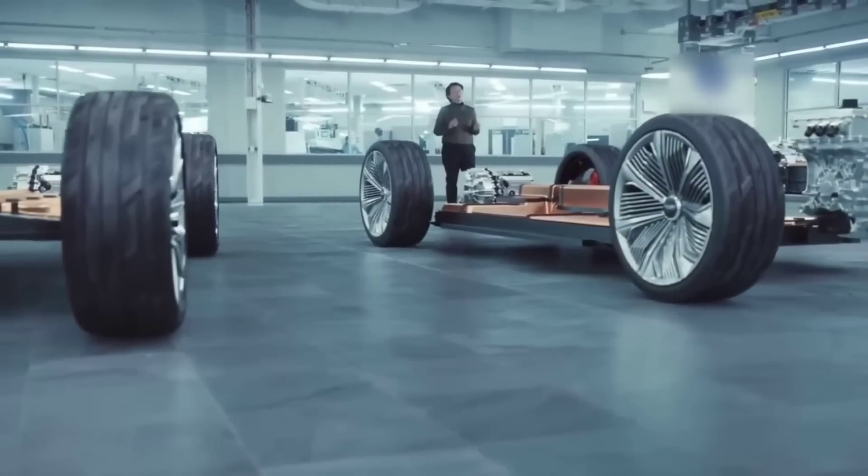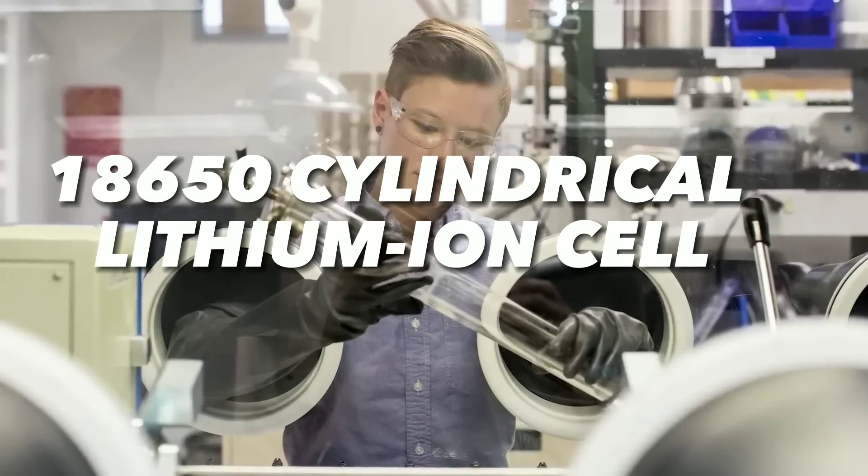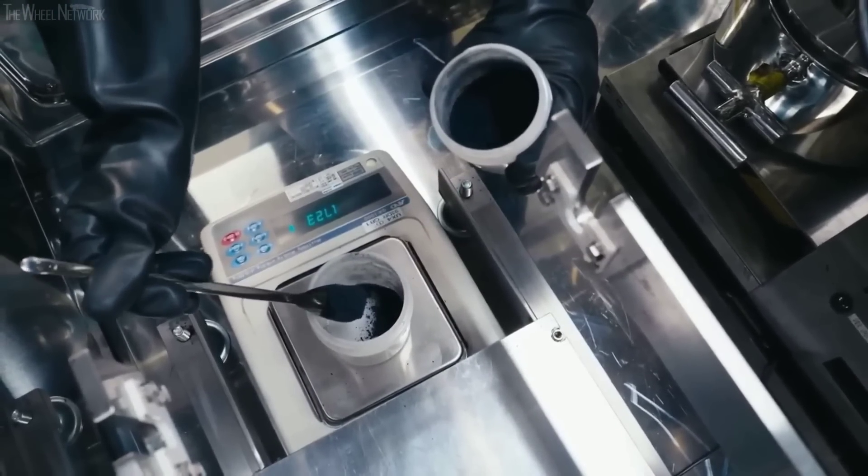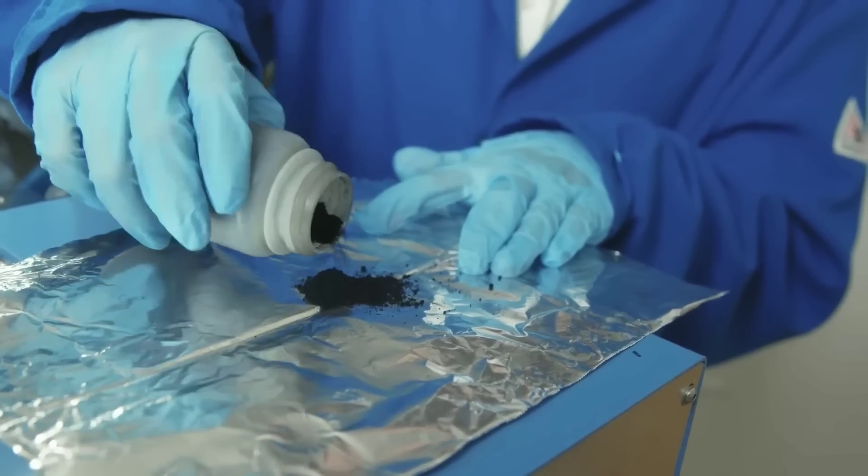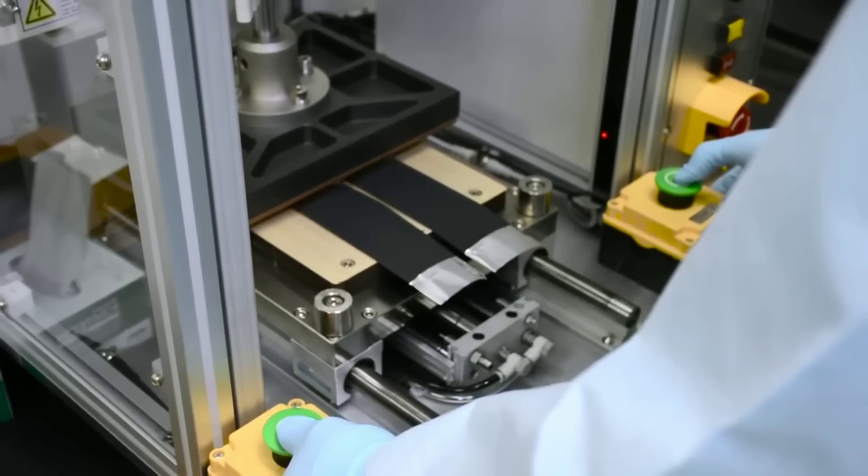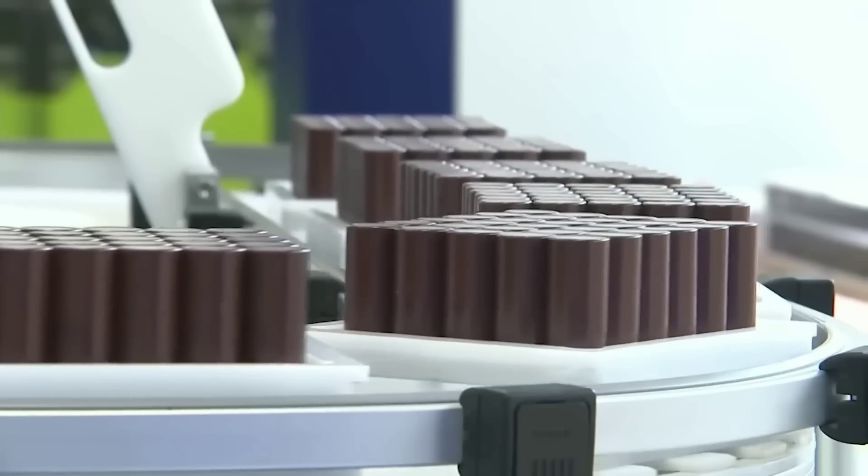By using this technology, Nanograph has enabled the world's most energy-dense 18650 cylindrical lithium-ion cell with a capacity of 3.8 ampere hours and an energy density of 800 watt-hours per liter. This cell provides a 28% longer run time than traditional cell chemistries.